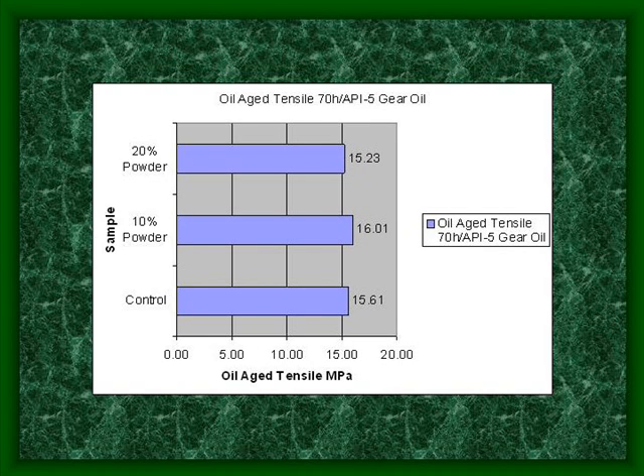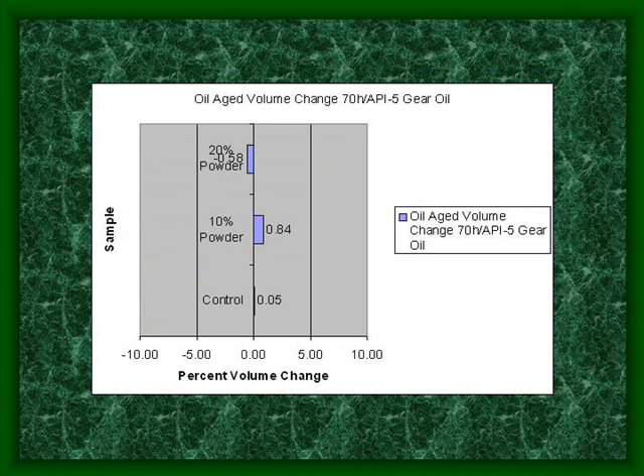The samples were tested for oil-aged tensile strength, 70 hours in API 5 gear oil. As you can see, the tensile strengths were equal in this case too. The oil-aged volume change under these conditions was essentially equal as well.